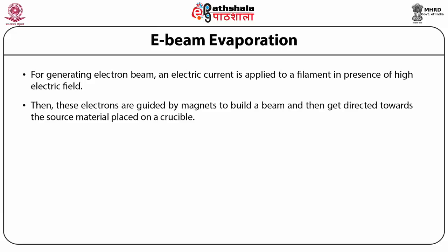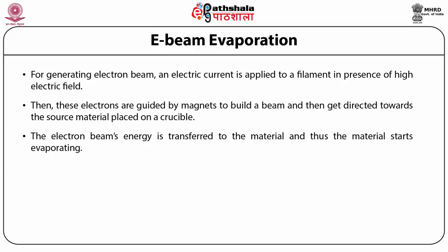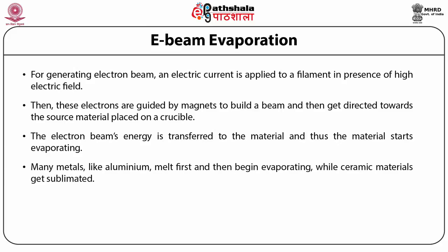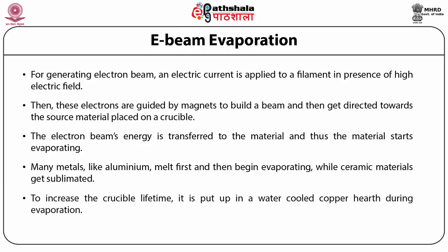Then these electrons are guided by magnets to build a beam and then get directed towards the source material placed on a crucible. The electron beam energy is transferred to the material, and thus the material starts evaporating. Many metals like aluminium melt first and then begin evaporating, while ceramic materials get sublimated. The vapors of the evaporated materials then travel out of the crucible, and thus the substrate is coated. In order to increase the crucible lifetime, it is put in a water-cooled copper hearth during evaporation.